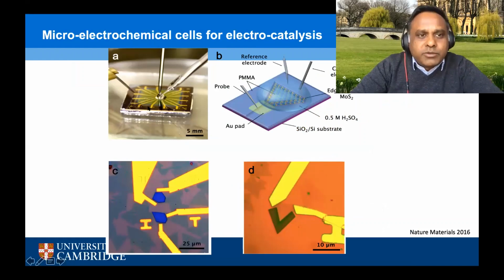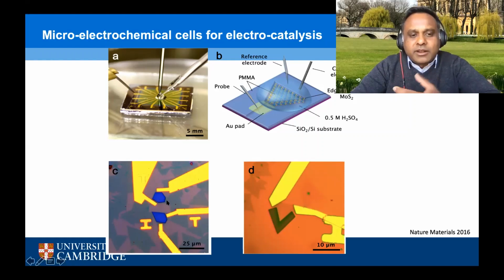And so we've pioneered these micro-electrochemical cells for electrocatalysis, which allows us to measure the electrocatalytic properties of individual sheets of MoS2 or tungsten disulfide, any transition metal dichalcogenide. And it simply involves patterning electrodes, similar to what we do for FETs, on as-grown CVD samples. And then we can open up windows on top of these TMDs and use electrolyte to do electrochemistry very locally on an individual flake, using the reference electrode, counter electrode, and the working electrode. And this gives us a lot of information about the number of atoms that are active in the catalysis reaction and so forth.